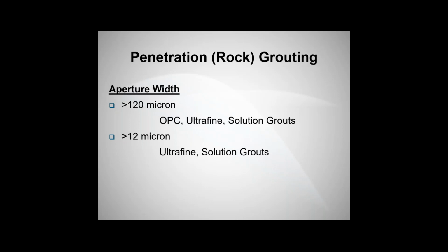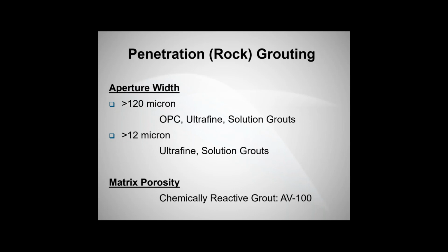Quick rule of thumb, greater than 120 microns in size, you're going to be able to get an ordinary Portland cement in there. And then as the fractures tighten, you may drop down into an ultrafine cement around 12 microns or somewhere in that range. And of course, if you are in a matrix porosity, more than likely, and not always, but most likely, you're going to have to jump into a solution grout or a chemically reactive grout like an AV-100 acrylamide.